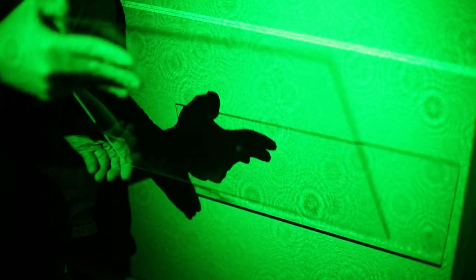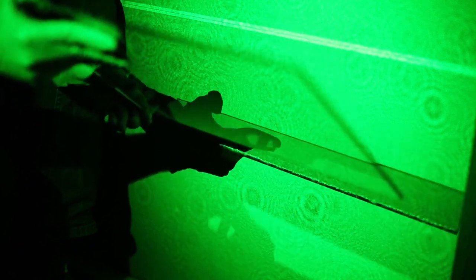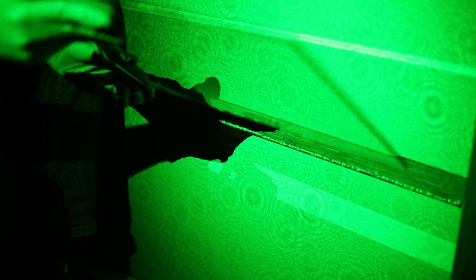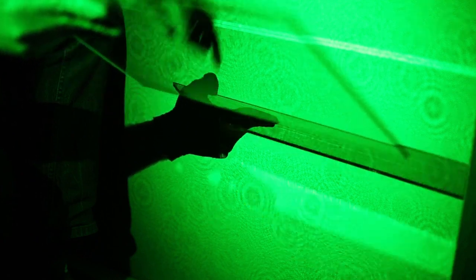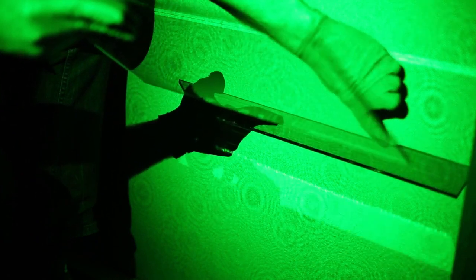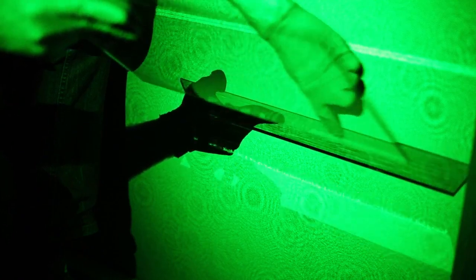New glass is constantly poured at the beginning of the production line, so the older glass is getting pushed forward. This pushing motion forms a pattern of parallel lines in the glass. You can make this pattern visible if you shine an expanded laser beam on the glass at a very steep angle and look at the light passing through. Depending on the orientation of the glass, you will see one of two different patterns.